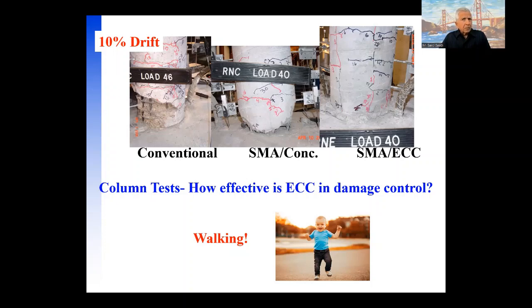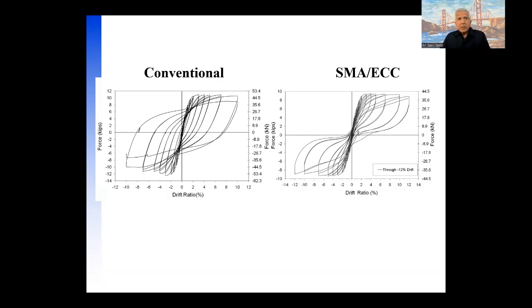Now you say, well, the basic attractive characteristic of ECC is its tensile strain capacity, but having that tensile strain capacity prevents damage in the cementitious material, even under compression. So when we have cyclic loading, we see that advantage here. So in the way of force displacement or force drift ratio, which is a measure of how successful a design works, we saw that in both cases, we did have good performance in terms of dissipating the earthquake energy.